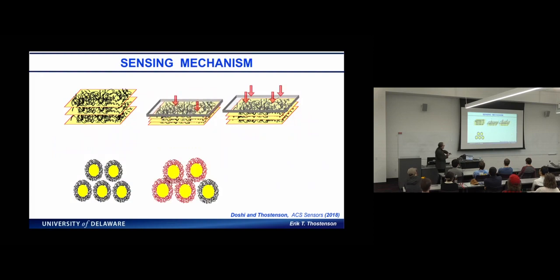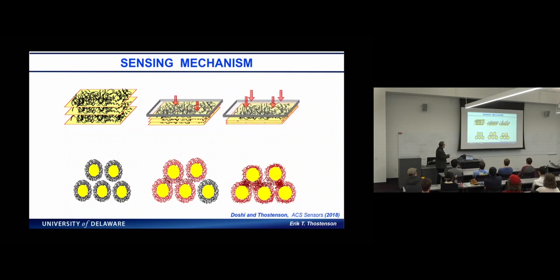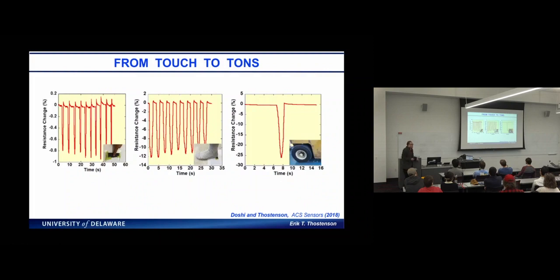And as I mentioned, this sensing mechanism is that we compress the fibers, and this is just a cartoon of how we're compressing the fibers touch, but then we're also compressing that foam-like interface, and that's changing the electrical conductivity. And so literally when we did this, it's from touch to tons. This is the example, for finger pressure, standing on it, like if it's the foot sensor in your shoe, but we drove over it with the forklift in the manufacturing lab. And there really is no damage to the sensor. So it's literally from touch to tons.